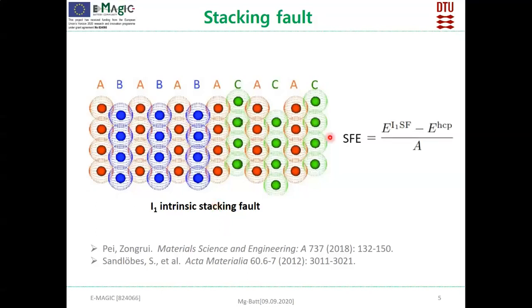And the stacking fault energy is normally calculated in ab initio or DFT calculations using this equation. So basically the first term indicates the energy of the structure with a stacking fault, and the other one, this EHCP, is the normal HCP system, divided by the area of the stacking fault. But to computationally calculate the stacking fault energy, the energy of the stacking fault structure is computationally very expensive because we have to calculate the stacking fault structure.